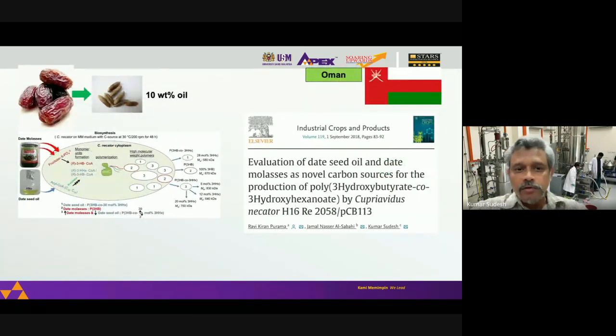And similarly, we also did a research collaboration with Oman. And you probably know Oman is a country that produces a lot of dates. And dates contain a seed, a kernel, which also contains about 10 weight percent oil. So we extracted the oil from this date seed. The seeds are normally not used, they are just discarded. And the oil in the seed can be extracted, and we tested its ability to be a carbon source for bacteria. And then we found that bacteria can use the seed oil and make PHA.